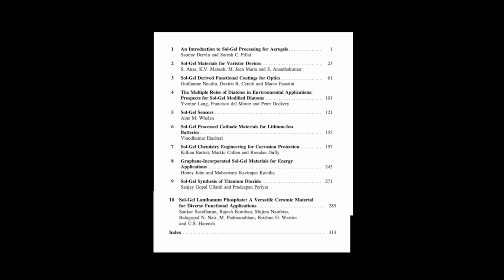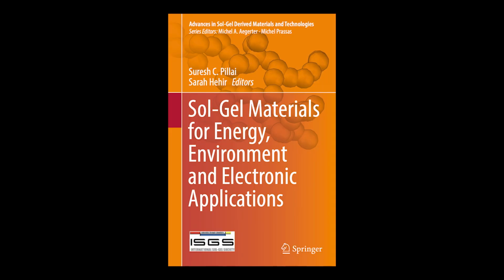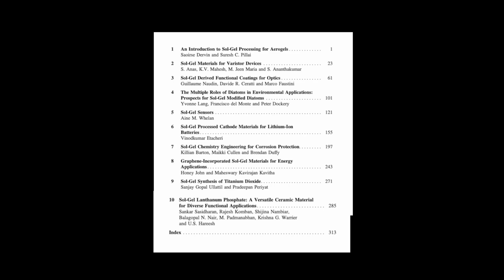Makes sense. The sources also emphasize that adding nanoparticles into the sol-gel coating is critical for performance. What roles do they play? Are they just fillers? Oh, they're much more than just fillers. Nanoparticles provide basically a triple threat. They offer mechanical reinforcement, making the coating tougher, they improve the barrier function, and they can also act as sources of active inhibition themselves. Firstly, they act as pore blockers. By filling in some of the residual nanopores within the sol-gel film, they reduce the overall permeability, which is vital for the initial passive barrier function.